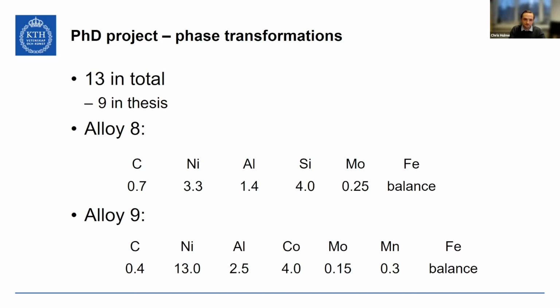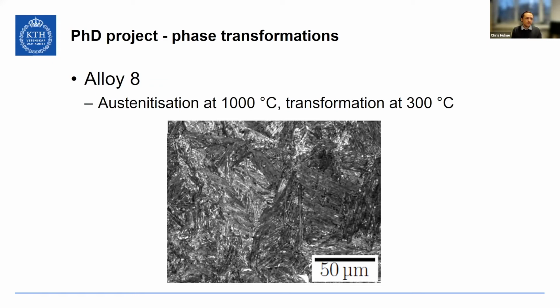Okay, so how did these look? Well, I hope it comes across okay on the slide. If it doesn't, go away and read my thesis, because there are lots of micrographs in there. I'm not going to go through all the micrographs today because I don't have time and it's probably really boring for people. But needless to say, I was able to form nanostructured bainite, as we moved away from the super bainite name slightly to help promote it within Rolls-Royce. So we got this nanostructured bainite in alloy 8, which was the high silicon with modest nickel content.